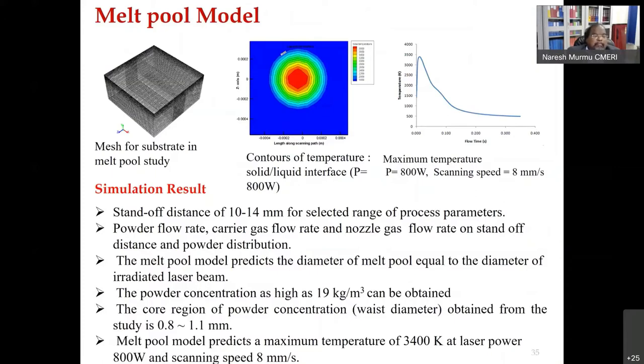And then finally, what simulation results were actually useful. One of the things that came was that by the contours of temperature solid liquid interface, we found that our power requirement of 800 watt is quite sufficient. Then came the standoff distance from 10 to 14 millimeter in the process parameters. And then powder flow area and rate of standoff per distance details we got. Then also we got the melt pool diameter equal to the diameter of the irradiated area. So this information became very critical, crucial for us.